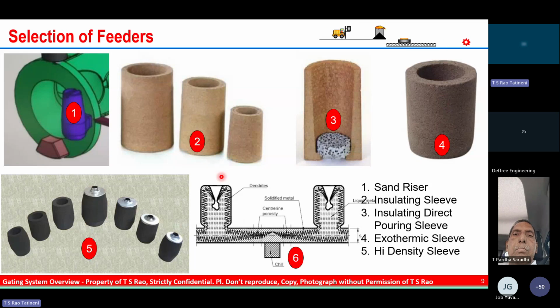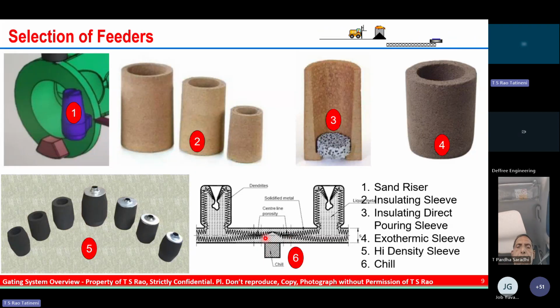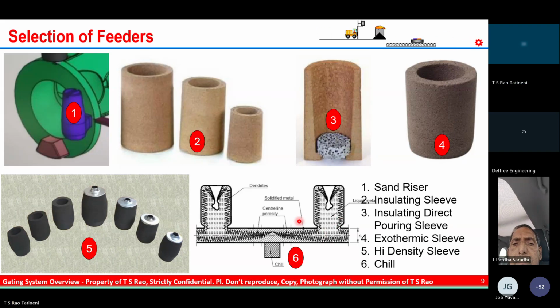The fifth one is high density or neck down sleeves. Here the modulus extension factor would be about 1.75 to 1.8. And the last one is a chill. So the purpose of the chill is to push the hot metal towards the riser so that the riser will feed the required metal at the particular junction. So these are the feeders.